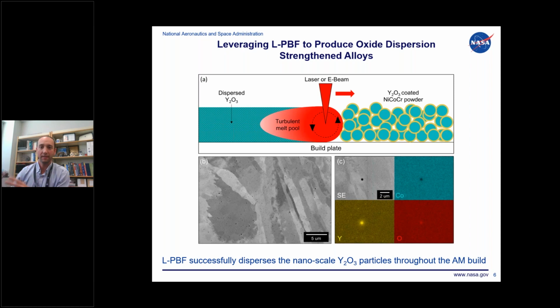So we would take this yttria coated nickel, cobalt, chrome powder, and we would put it in our printer, and through some trial and error, we were able to find parameter sets that evenly disperse that coated yttria into our metallic build.